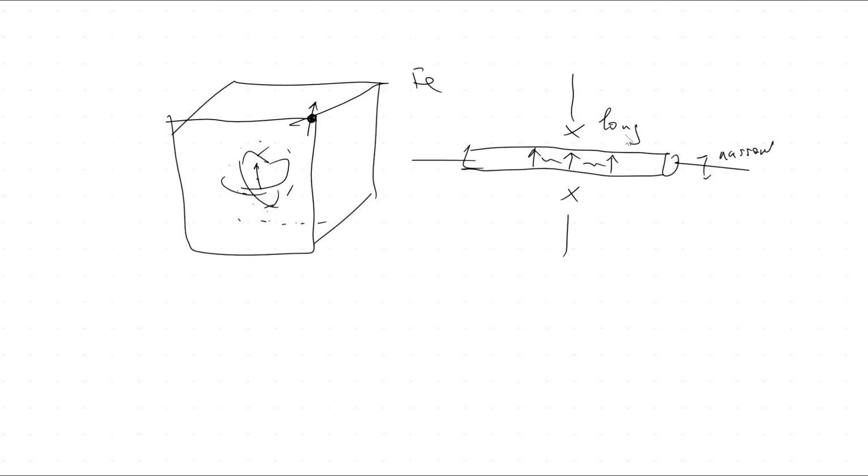That's what the wire is. And therefore, if we change the dimensions of the shape, then we will have different interactions between magnetic moments along the wire and perpendicular to that. And again, strong interaction means that our wire wants to be magnetized along this direction, and that forms our easy axis, and that would be the hard axis.